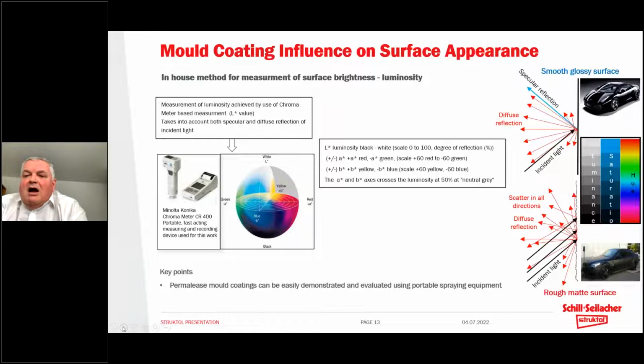So we would have a complete absorbance of light, if you like, to a complete reflection of the light. And when we change the surface layer, when we change the surface topography, then we can impact or directly influence the shininess or the glossiness, and therefore the reflection, the brightness that we can achieve from this surface. One maybe good example is to look at a very highly polished new car. If you're ever lucky enough to own such a car, you would see that the very smooth and flat surface would produce a very bright appearance. The light is reflected very orderly, and we see a high degree of shininess or brightness from those colours.